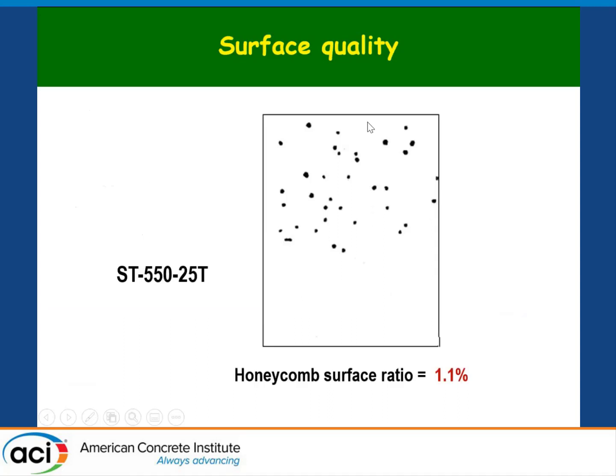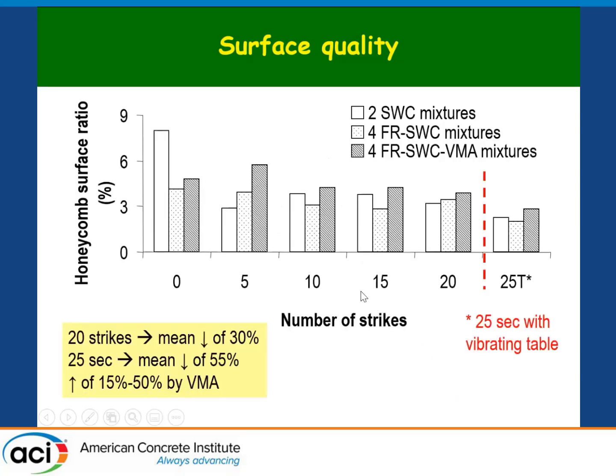And finally, we looked at surface quality, looking at the honeycombs. So using surface image analysis, determining the amount of bug holes divided by the surface. This is 1.1%. And you could see that 4x8 samples without any striking, just filling them in one layer, will have a lot of bug holes. And those amount of bug holes are decreasing regardless of the mixture with the striking of the surface of the concrete samples, and then even more reduced with the vibration.